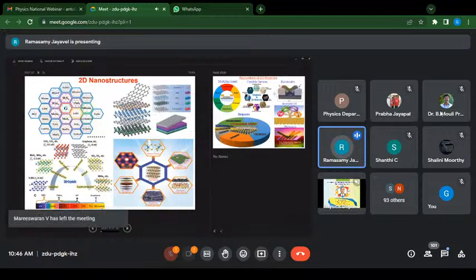When it comes to the properties of this material, these are all multifunctional materials. For example, hexagonal boron nitride is a very perfect insulator with an energy gap of more than 5 electron volts, and materials like MoS2 and tungsten selenide are all typical semiconductors with an energy gap of 1 to 2 electron volts, and materials like chromium oxide and chromium sulfide are half metallic, and graphene is a zero band gap material, which is a semi-metal, sometimes it's metallic, and there are some materials which are highly metallic, and some materials will have very extreme conductivity, and these materials are called superconductors.